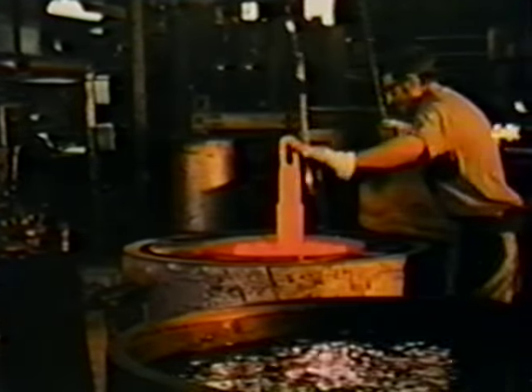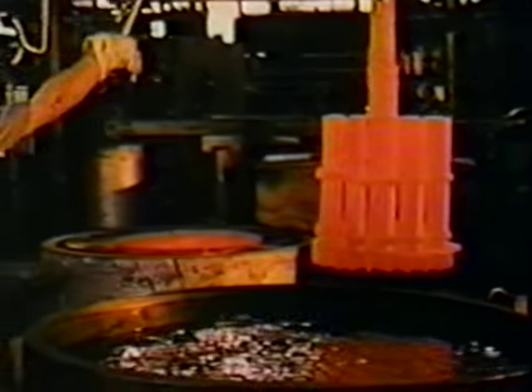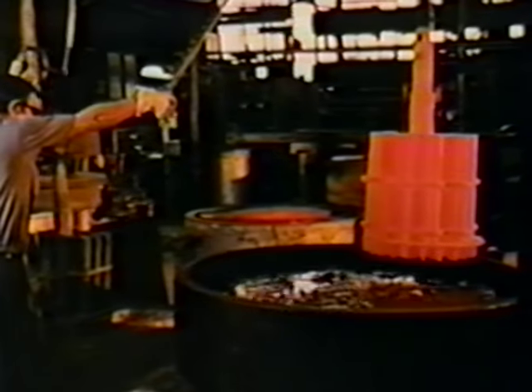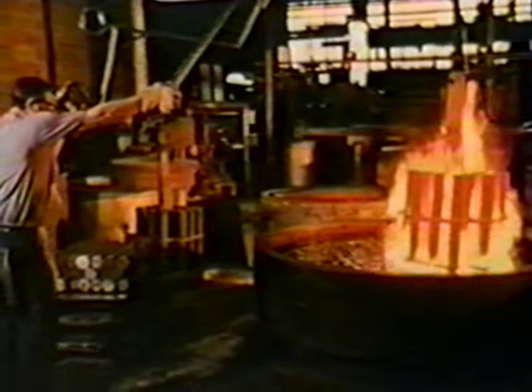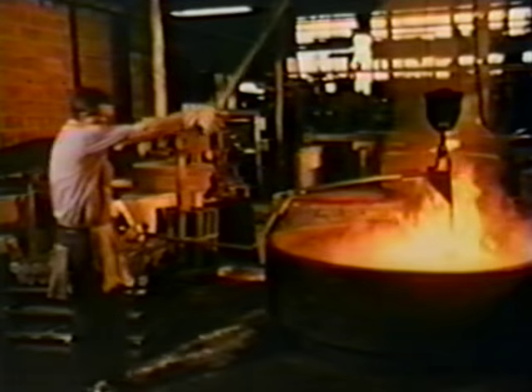Besides this, you harden your parts in the oil here, and then you draw them in those two draw furnaces over there. And that softens them a little bit. They want to get a certain hardness, and a certain hardness after draw, too, see? When you harden them, they want around 500 Brinell or 600 Brinell for hardness. Then when you draw them, they want it down between 300, 250, or 260, something like that, 65.